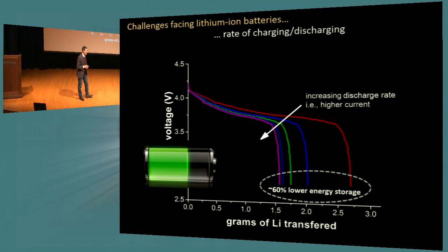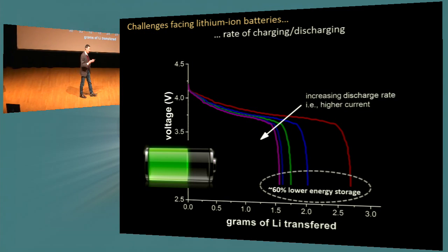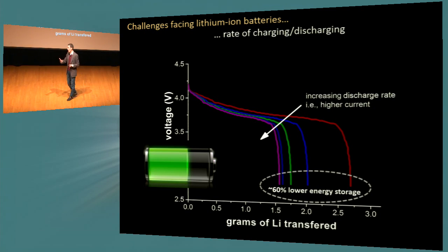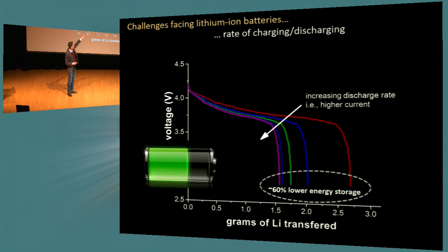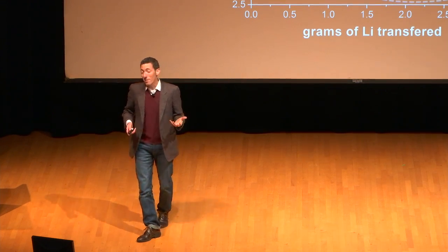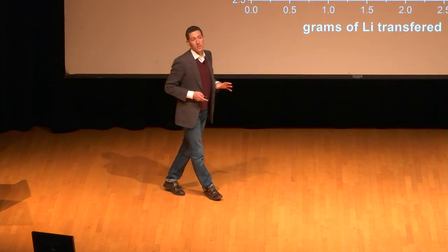And this is a favorite. I always like to talk about this one. Everybody wonder why when you go to work, you go to school, and you charge your battery overnight. And you get on there and you do a few things, check your email, and it's 100%. It's 95%, maybe mid-morning, maybe right before lunch, it's like 90%. And then like 20 seconds later, it's 20%. You're just like, what? Well, your device is really looking at the voltage of your battery and it's sort of sitting in that flat part there. And it's kind of guessing, because it doesn't really know where it is on that. And all of a sudden, the voltage starts going down that cliff. And all of a sudden, your device is like, panic. I've got to tell my owner. I've got to tell my owner we're about to run out of the battery. So that's what's happening.